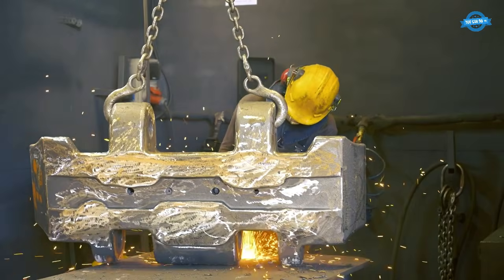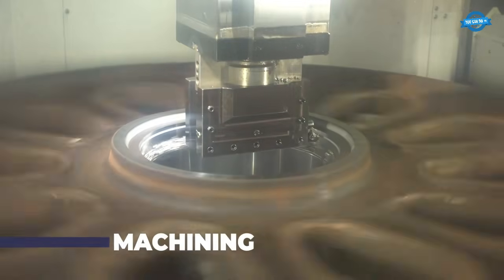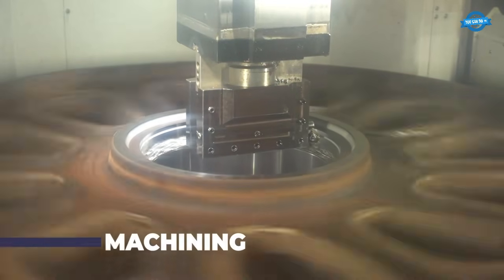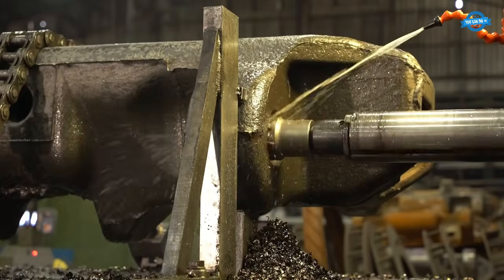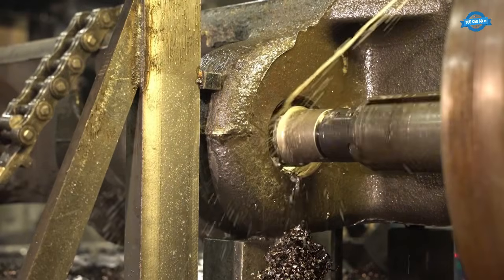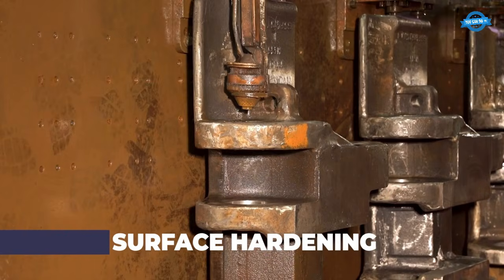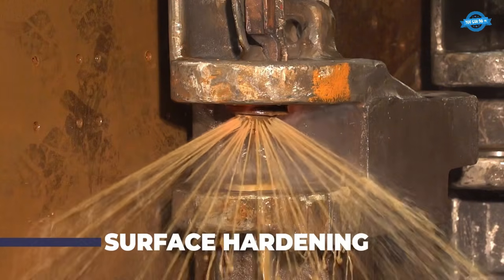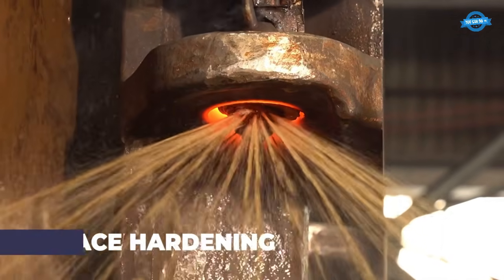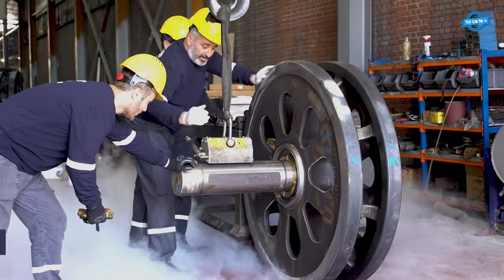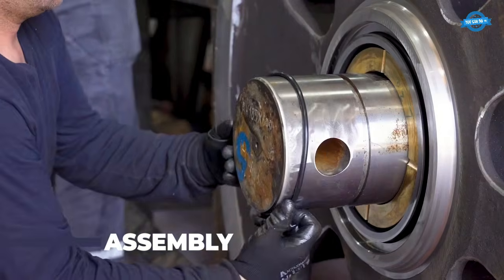Grinding removes flash and excess material. CNC turning and boring finish the critical surfaces. Surface hardening applies a localized quench to the zones that will see the worst friction, sprocket teeth, roller contact bands. Then magnetic particle testing hunts for hairline cracks that would otherwise stay invisible until the part was already in service.